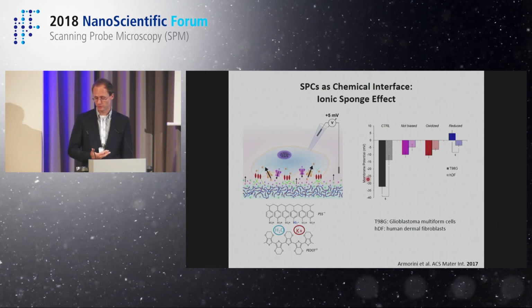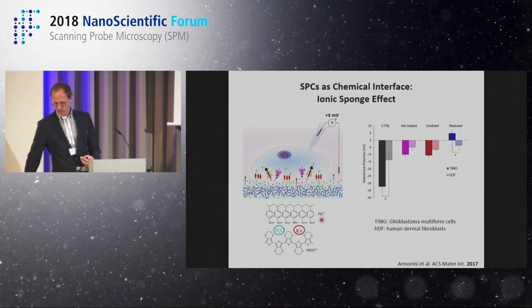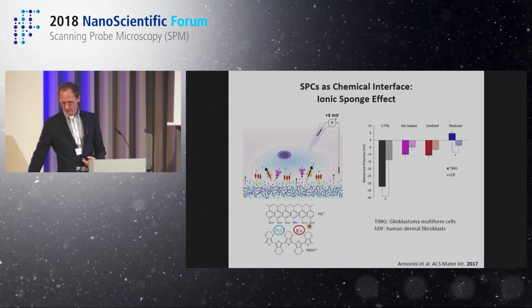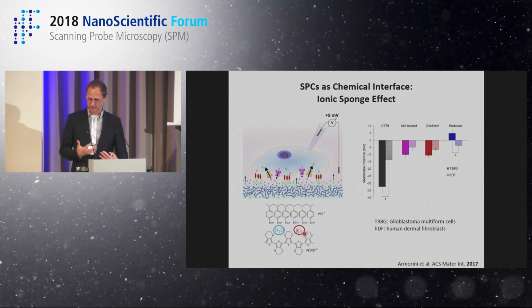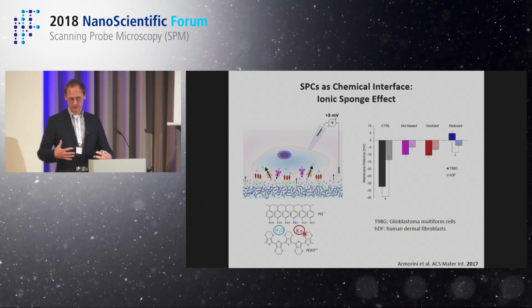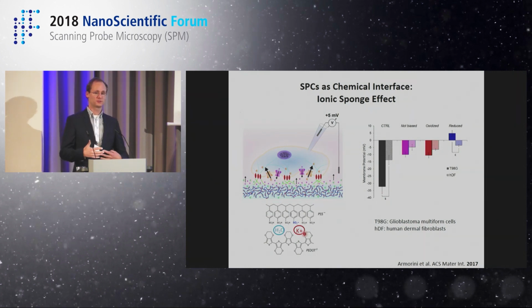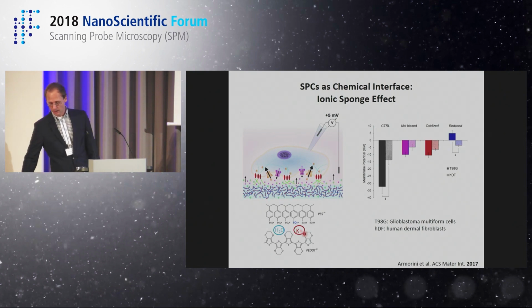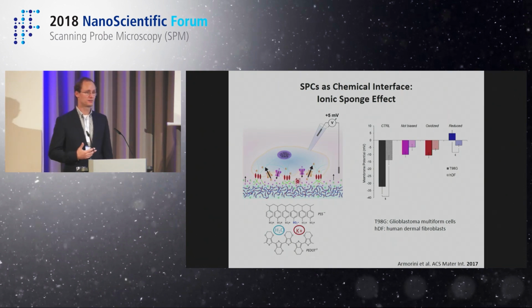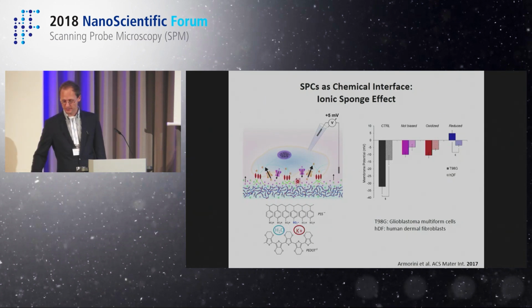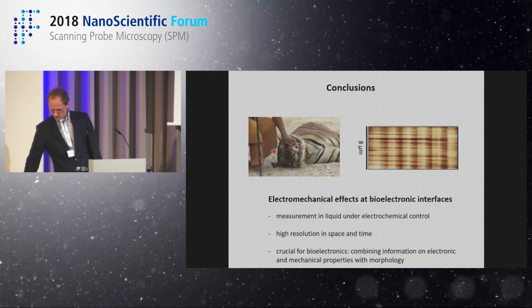And now, thinking further of what actually is happening, imagining this material as a kind of ionic sponge, it's clear that you have a system where you can accumulate, for example, if you do the reduction in a solvent that contains potassium, you can accumulate potassium and you can release it. And the sponge effect, that release of ions, is something that we think is locally acting here on the electrochemical potentials that build up at the membrane. And this release of ions is actually what's impacting then on how cells behave on oxidized or reduced materials. Just to keep further in telling the story.